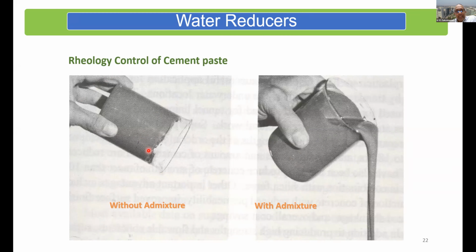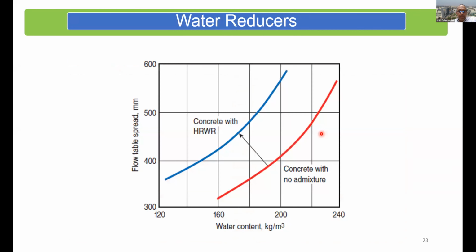a rheology measure of cement. And suppose I take cement paste, which has a very low water to cement ratio, this is how it would fill inside a container. It won't empty out. If I add a few drops of this high range water reducer, I reduce the yield stress and then the cement paste starts to flow.